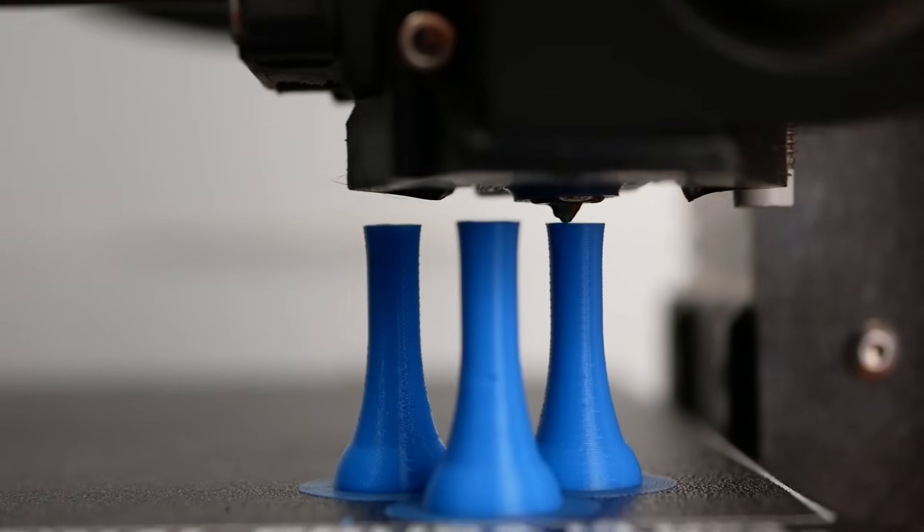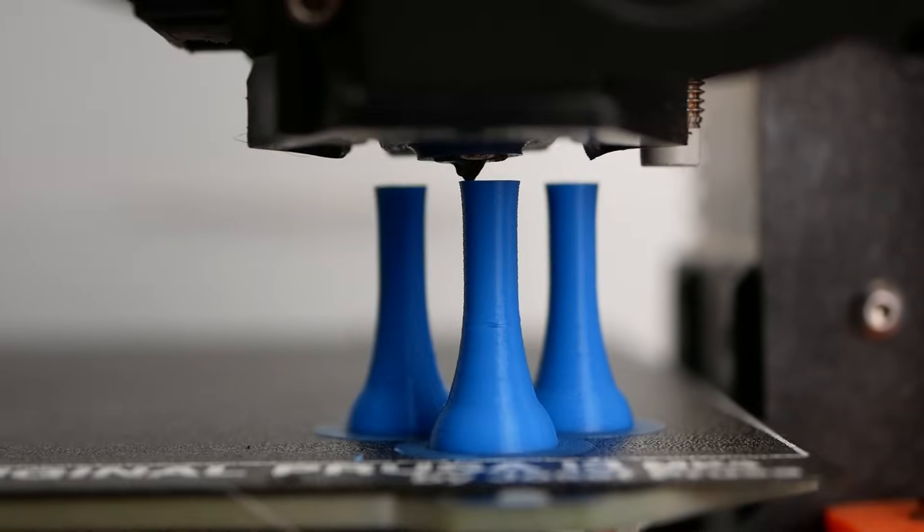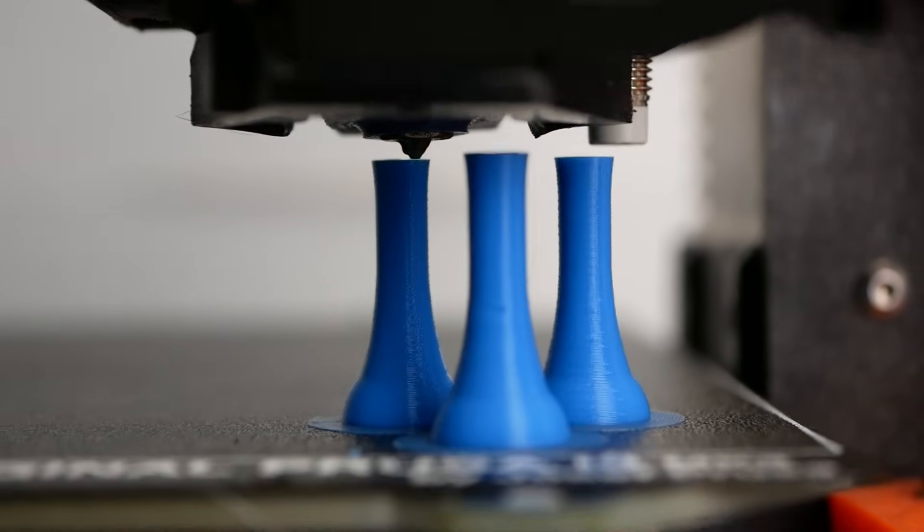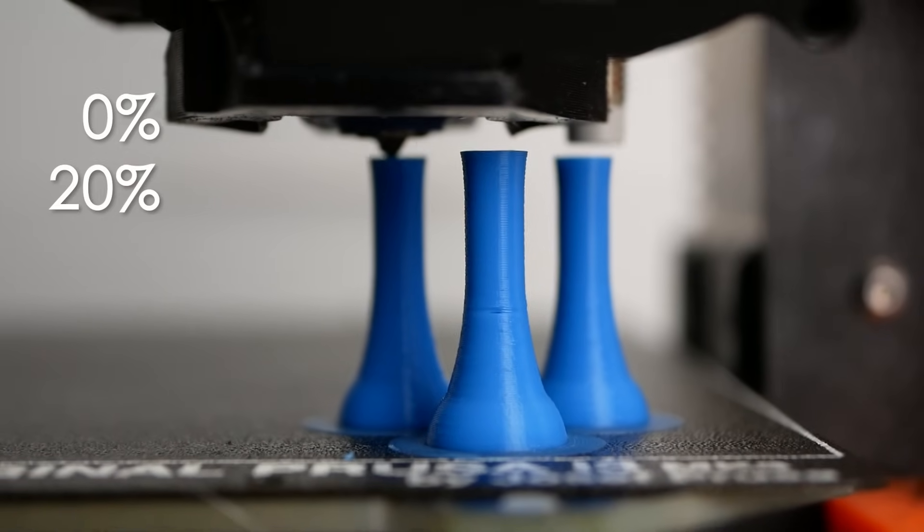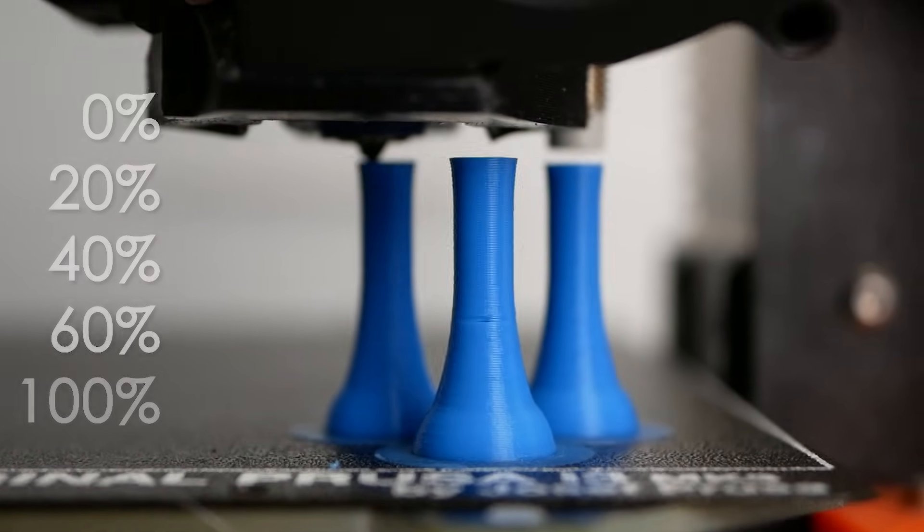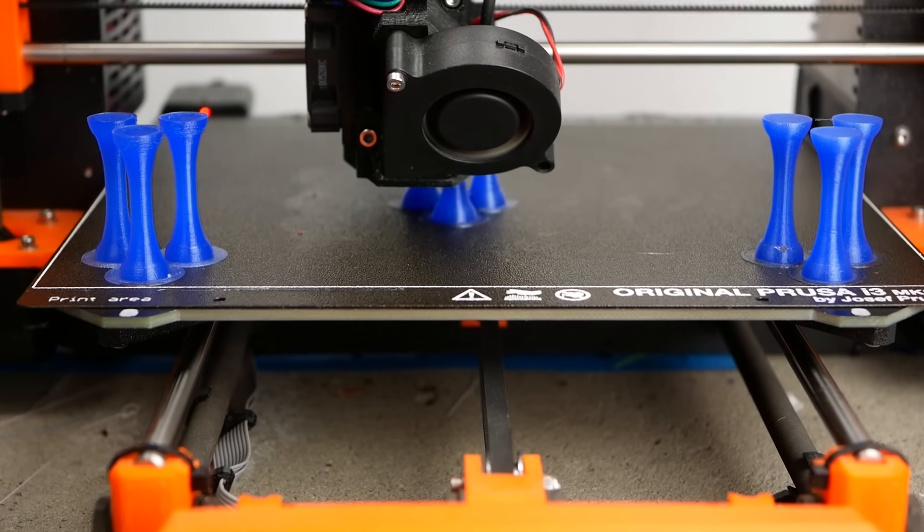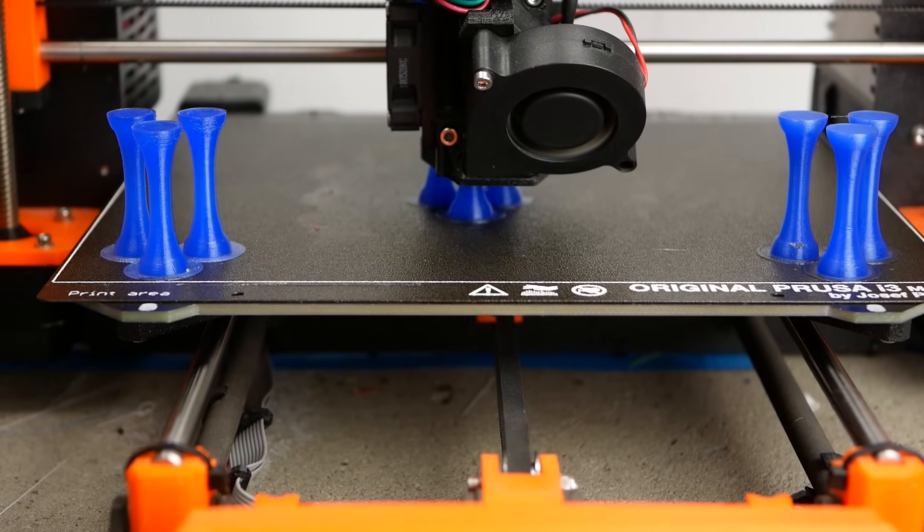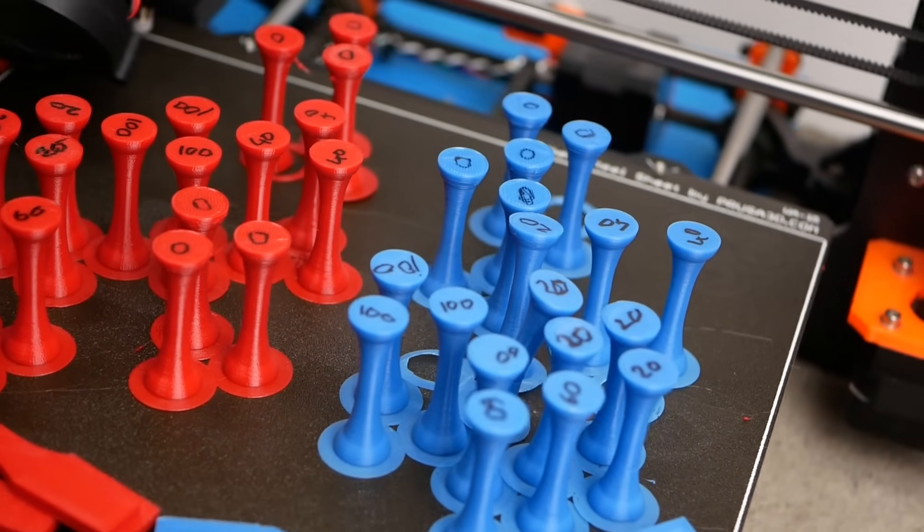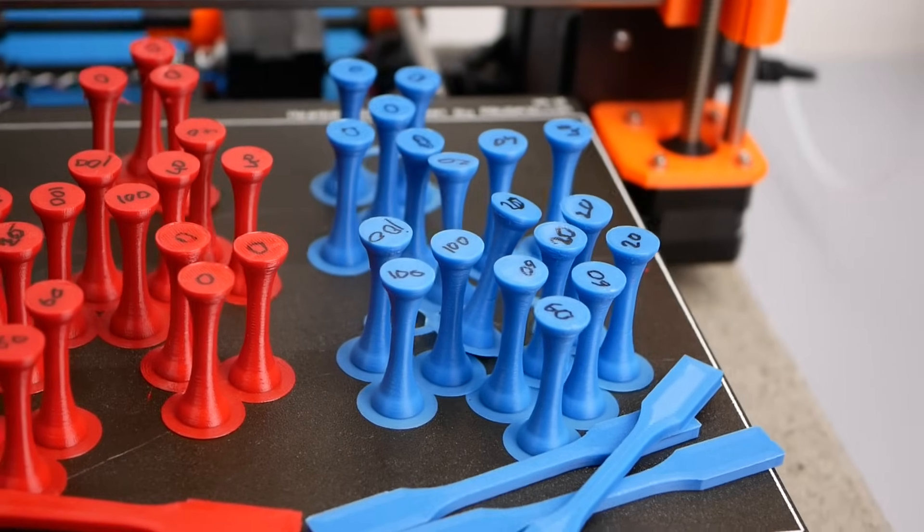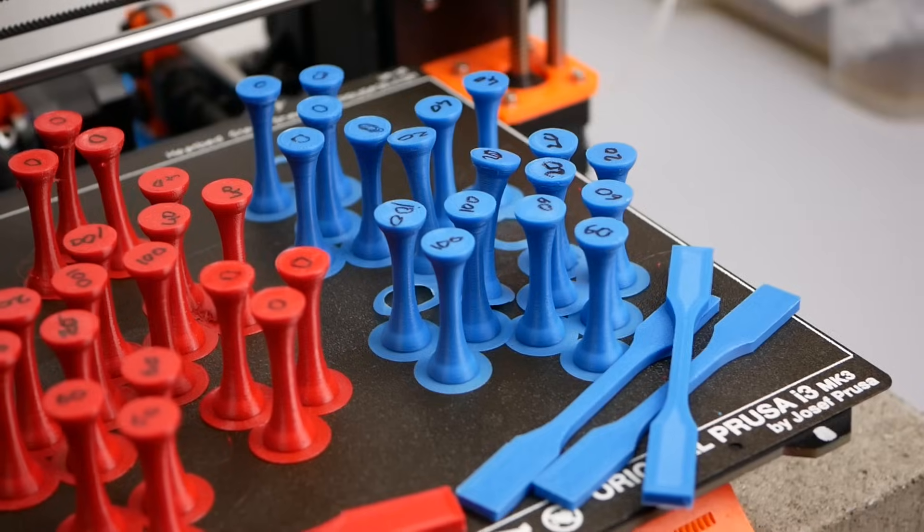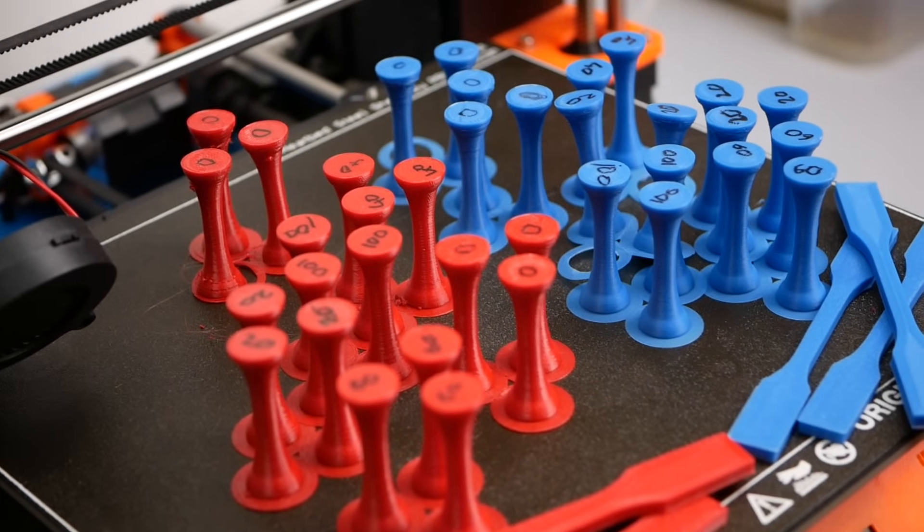For this series of tests, I've printed three samples for five different fan settings which makes 15 samples in total for each of the materials. The fan settings I used were 0%, 20%, 40%, 60% and 100%. I printed all of the samples in a single print job where each group of samples was finished one after another. In order to compare the strength values at different fan settings to a baseline, I also printed three horizontal dog bones but these ones only at one single fan speed since I boldly state that there won't be a significant change regardless of the cooling.